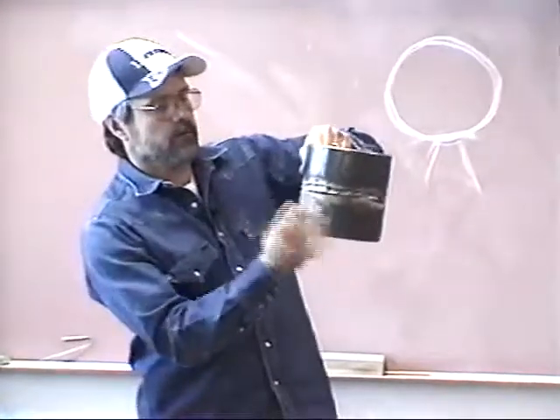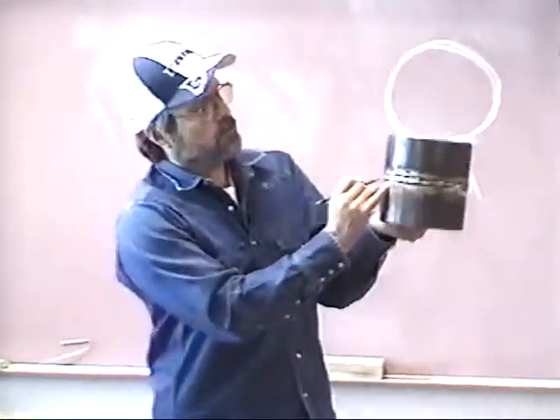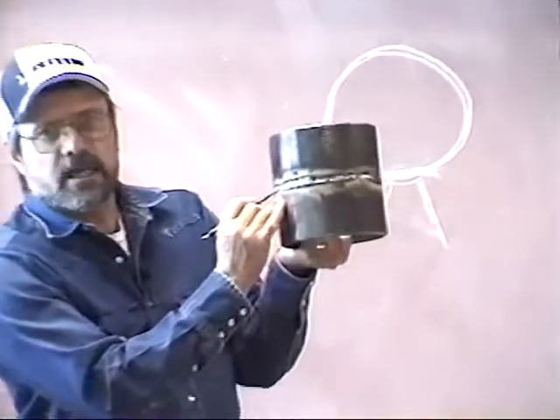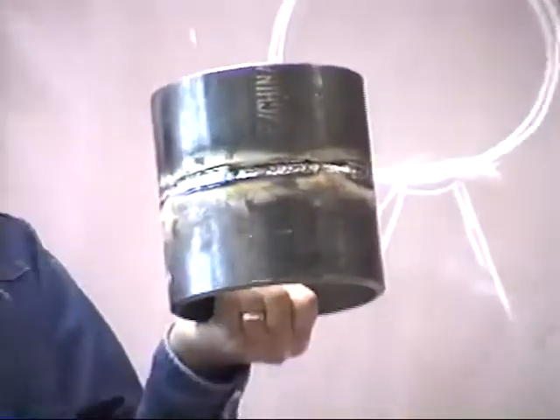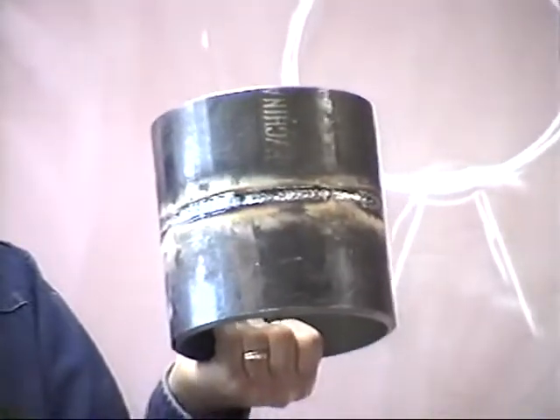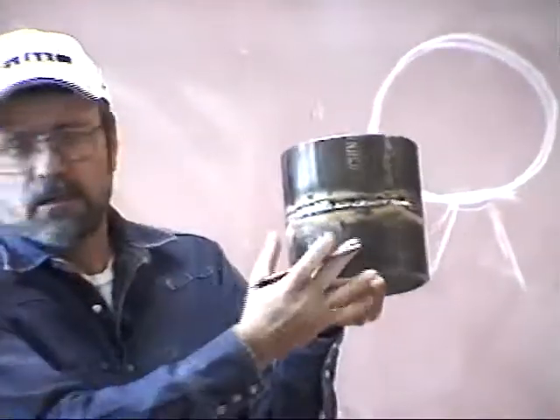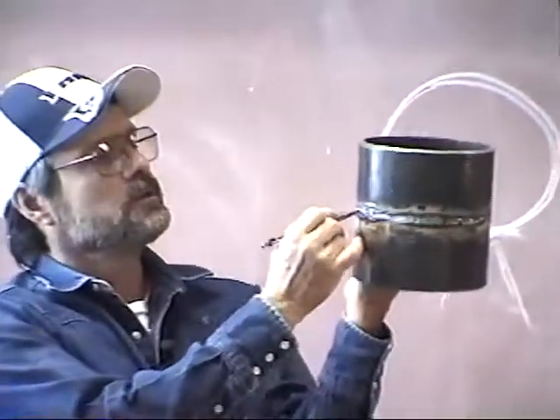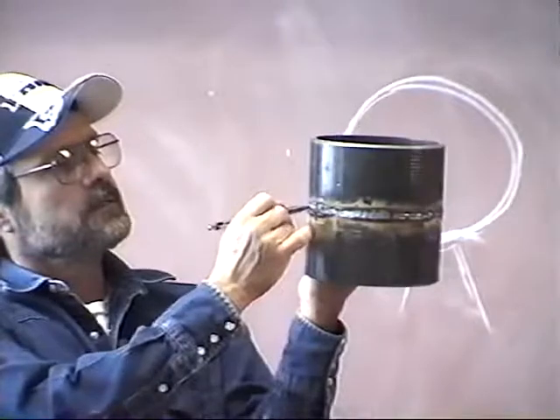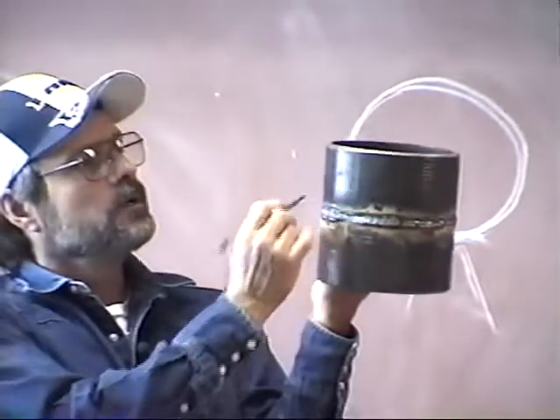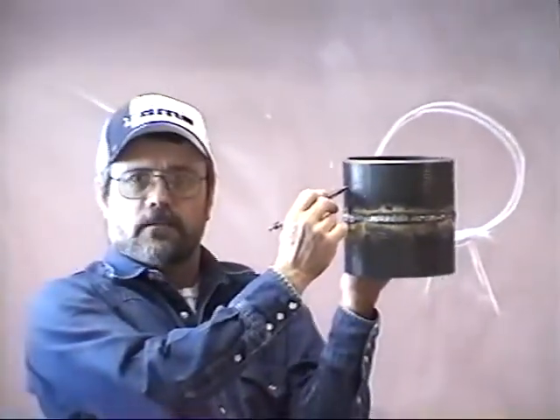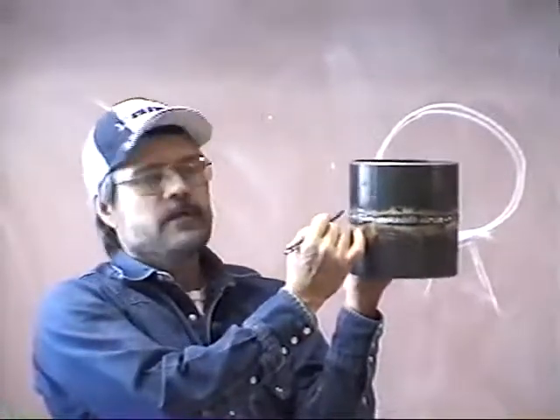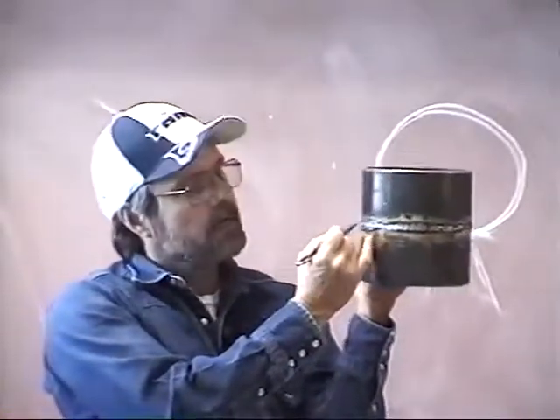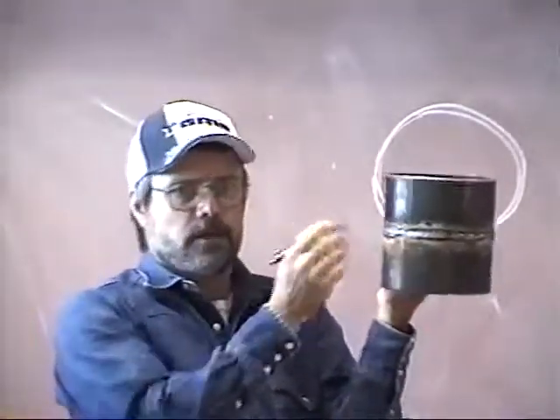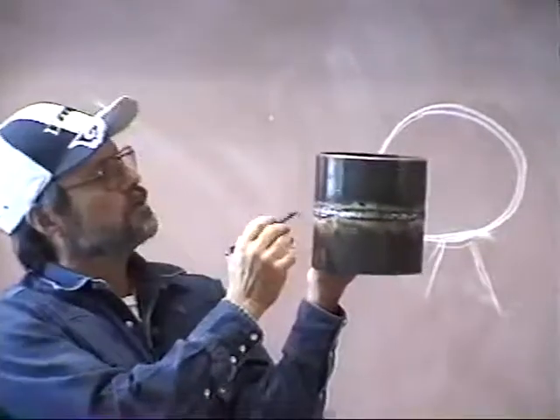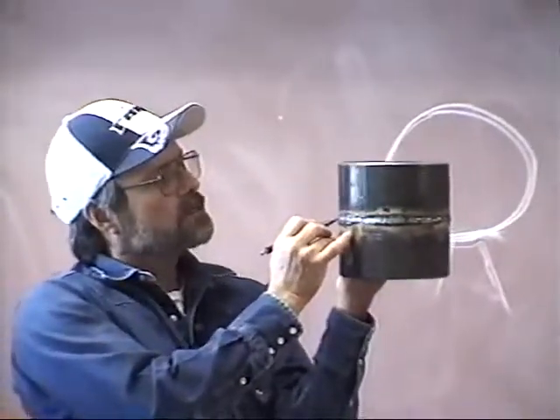and you're welding around here, and it doesn't matter what position you're in, you're going to watch that keyhole. And you want to listen for that sound of penetration. If you're hearing that sound, you're probably getting through. In the 2G position, you want to be careful, because if you don't have enough of an up angle, you're not going to tie into this overhead pipe very well, and you're liable to get internal undercut on the top side. So watch your rod angle, but we'll get into this more later when we get into the welding 2G position. Basically, watch that keyhole.